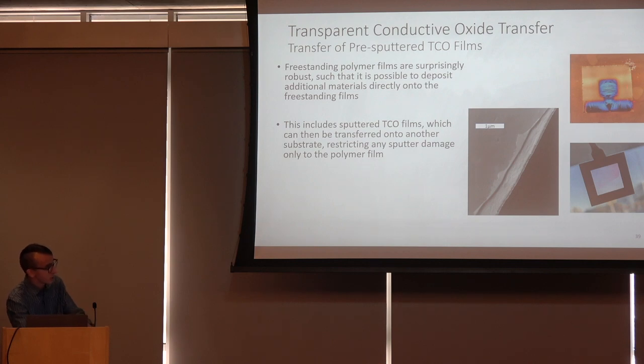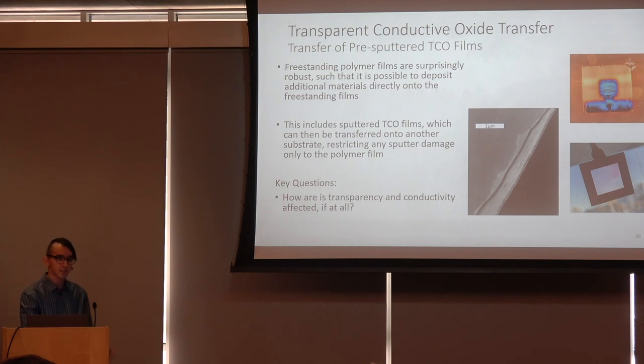And then if you want, you can also strip away the polymer by a variety of techniques. So it's very faint, but there's this line right here. Everything above it has conjugated polymer. It's a bilayer. And then everything below it is just ITO. And this film was just dipped in chloroform very gently and then pulled back out. So some key questions that we want to ask is, how is the transparency and conductivity of the TCO affected, if at all? And how difficult is the transfer?